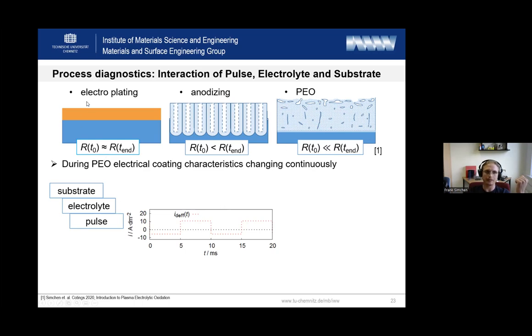In conventional electroplating, galvanic processes, you apply electrically conductive metal on another electrically conductive metal, so the resistance is not changing. In conventional anodizing, you apply aluminum oxide coatings on aluminum, but this aluminum oxide coating is still filled with pores, and the pores are filled with sulfuric acid, so the resistance is not increasing strongly. But doing PEO, you create 50 or 100 micrometers of crystalline oxide, and you have here some channels to the electrical active interface zone. So here take place a lot of interesting electrochemical subprocesses, and they all interact with the electrical pulse.